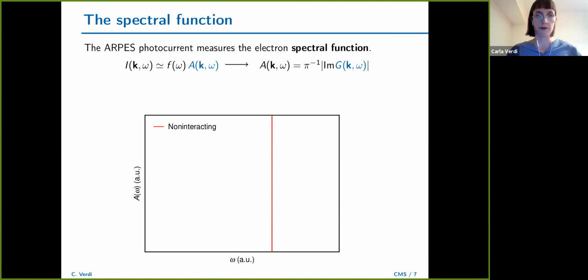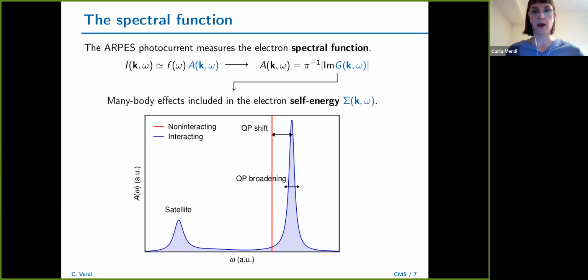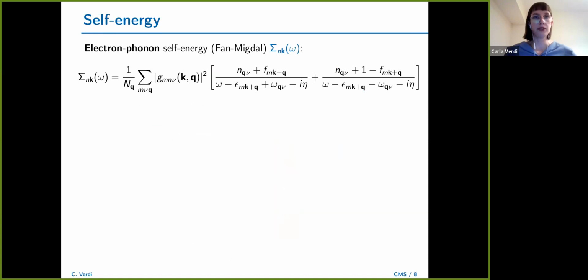Now, if we just take a very, very simple representation of what happens to our electrons in the material, if we have a theory where the electrons are non-interacting, the spectral function will basically be a delta function peak. And then when many-body interactions are switched on, then what happens is that this quasi-particle peak can shift, it broadens, and there can also be these additional features that we call satellites appearing. The many-body effects are included by a so-called electron self-energy. And this is what we are interested in calculating, basically. The electron-phonon self-energy, the dynamical electron-phonon self-energy, is given by this expression here. I will briefly walk you through what this all means.